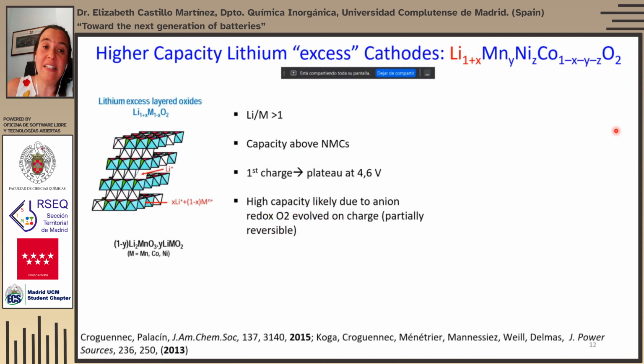Another strategy that is being investigated is the use of lithium-excess layered materials. This material, and actually what I'm going to be talking about from this point, are materials which are not in commercial batteries yet. The materials I talked about before are the materials that make it into batteries for the time being. But these materials have a lithium to transition metal ratio which is larger than 1. This means that in one interlayer between oxygen lattices, you have only lithium, but in the other layer, you have a mixture of lithium and manganese.